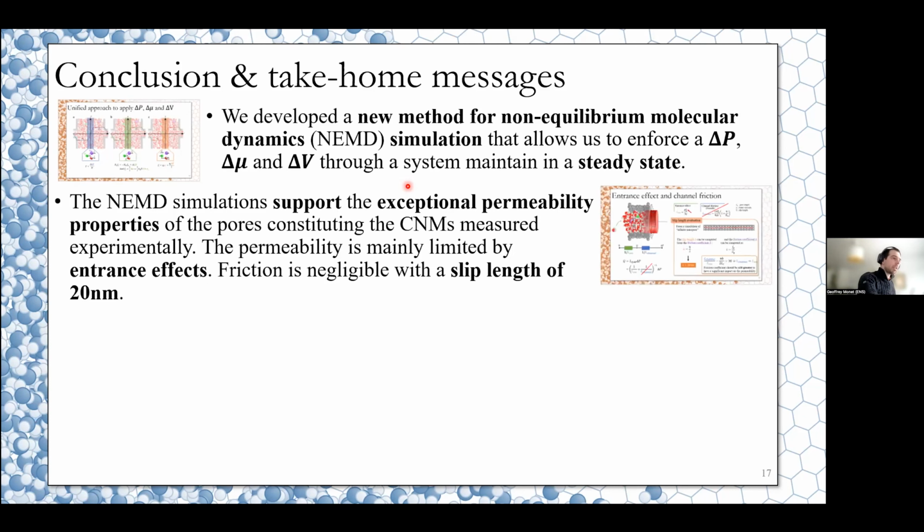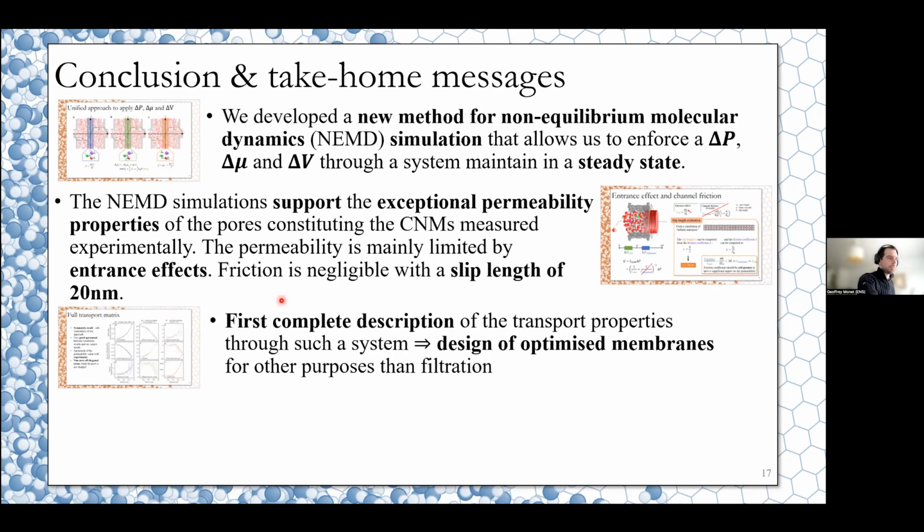So in conclusion, I will just summarize what I said. We saw together that we developed a new approach to perform non-equilibrium molecular dynamics simulation under the effect of pressure, chemical potential, and electrical potential drop, while maintaining the system in steady state. And thanks to this approach, we found back the exceptional permeability properties of carbon nanomembranes, and we saw that the permeability is actually mainly limited by entrance effects.